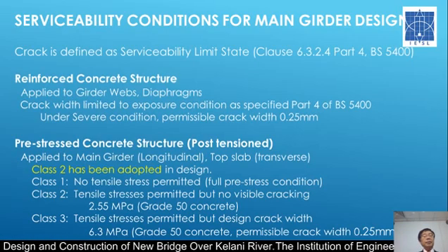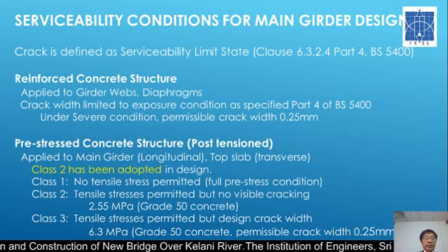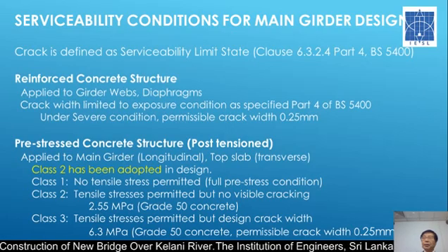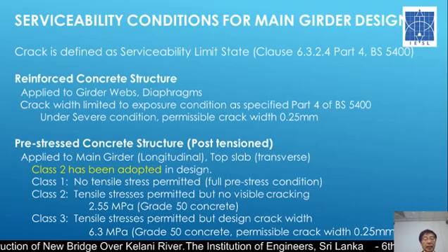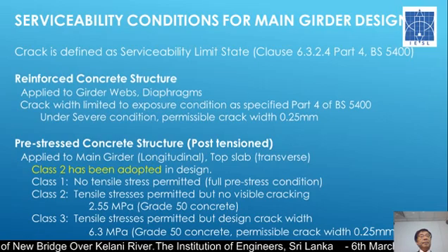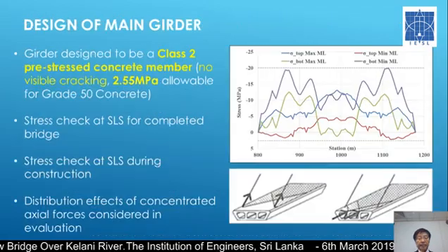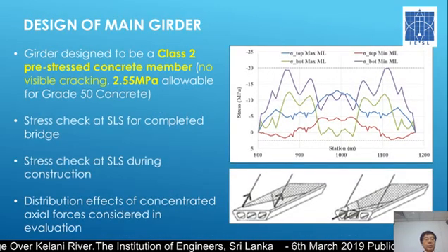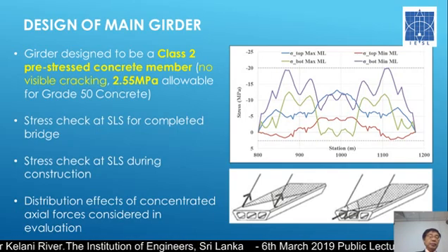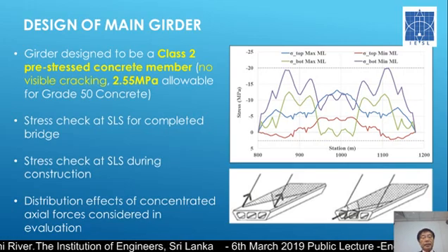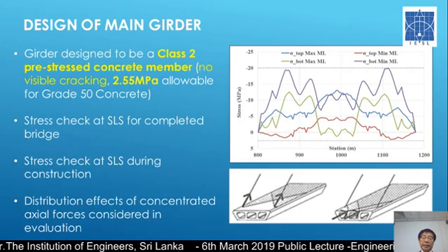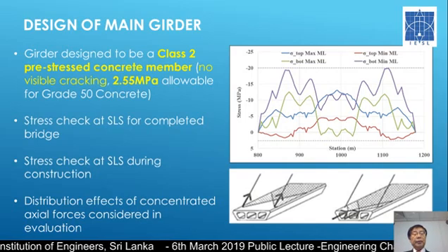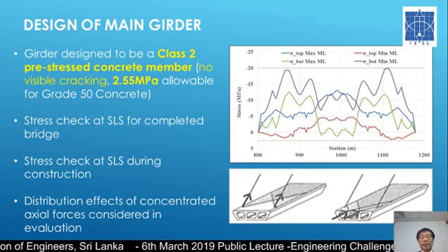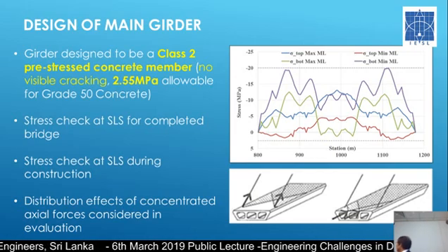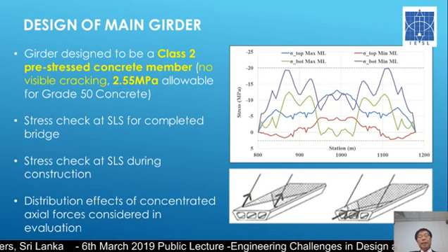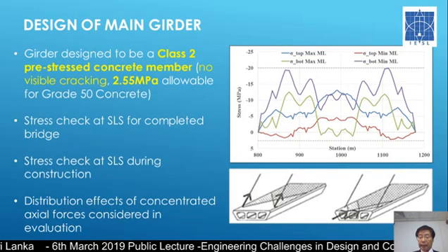But for the pre-stressed concrete structure, for the longitudinal girder, we use class 2. I'm not sure you know that category, which allows some tension but the crack is not visible. So that is class 2. For this class 2, the permissible concrete tension is defined as 2.55 megapascals for grade 50 concrete. So the design has to be made so that the tensile stress does not exceed 2.55. The right-hand side chart shows the stress, and the bottom dotted line shows the 2.55. All the stress is above it, which means it is on the compression side, so there's no issue of cracking theoretically.